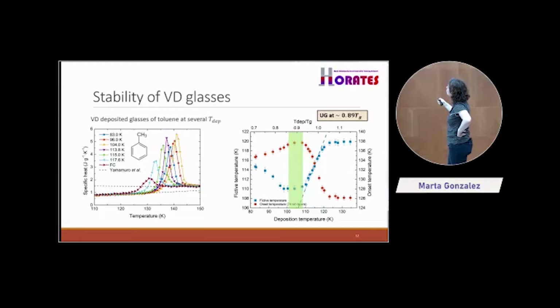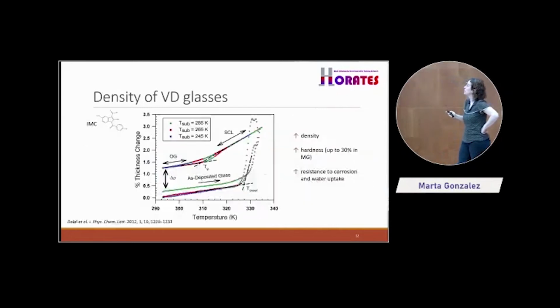So at this region, more or less, in toluene is around 0.9. We have the most stable sample kinetically, and this is fictive temperature, and it's related to thermodynamic stability, so the lower, the more stable, okay? But you see that what I was telling you, we can tune the properties of our film, okay? The stability of our glass. Okay, this is regarding thermal stability, kinetic and thermodynamic.